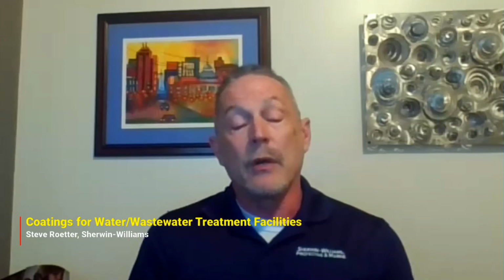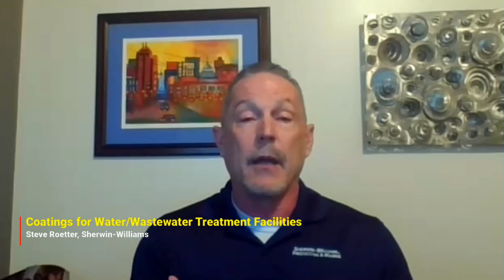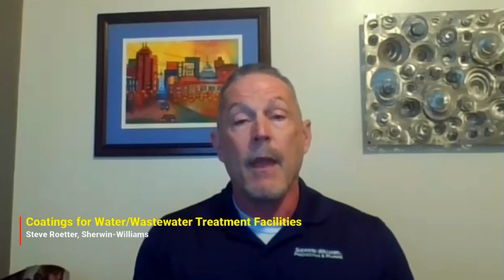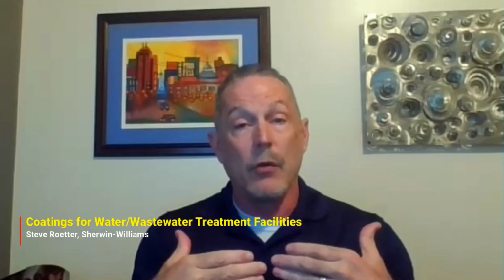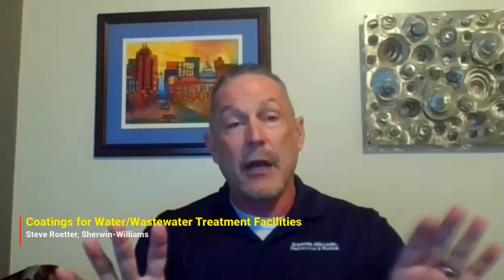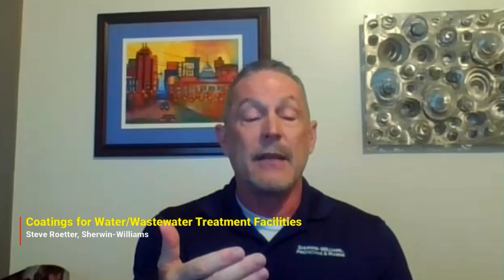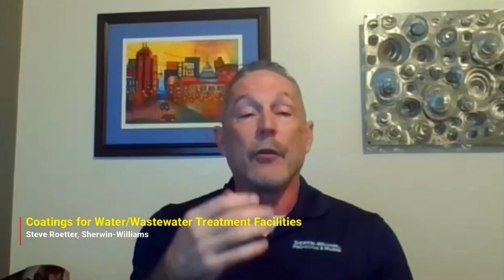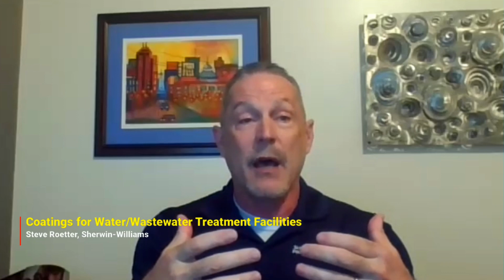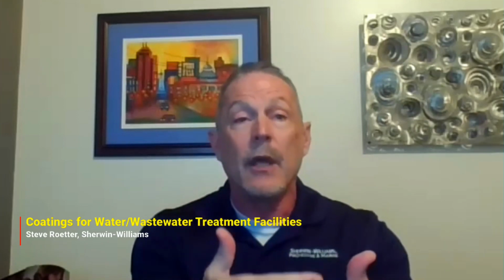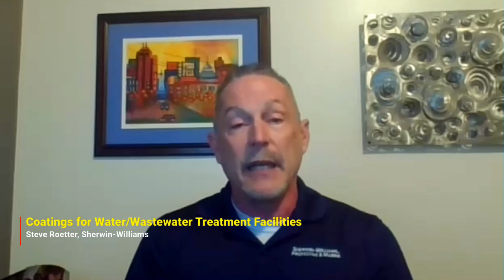So a challenge to the owner and engineer when you're developing a repair and a lining plan is you have to figure out how much concrete has to be removed from that surface to get down to sound material that is not contaminated with sulfates. As these sulfates penetrate into the concrete, you may have a layer where the sulfates are present, but the concrete still seems like it is sound. If you leave those sulfates in there and you line over them, those sulfates will continue to act on that concrete over time, and they can deteriorate the concrete underneath your repair and your lining and cause significant problems.